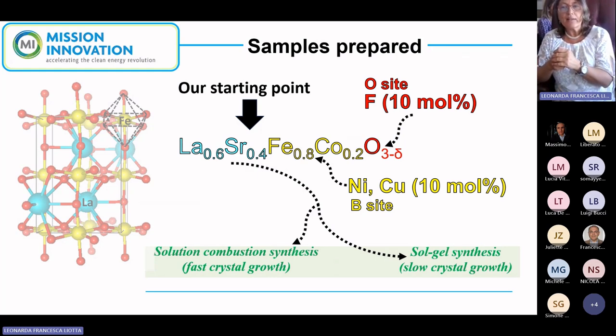And we check the effect of the B-site dopant, nickel and copper, also in the presence of 10% molar fluorine at the oxygen site. Fluorine has an indirect effect on the mobility of the oxygen vacancies. So it does not increase the oxygen vacancies, but increases the mobility of the oxygen vacancies, attracting the metal cations in the perovskite.